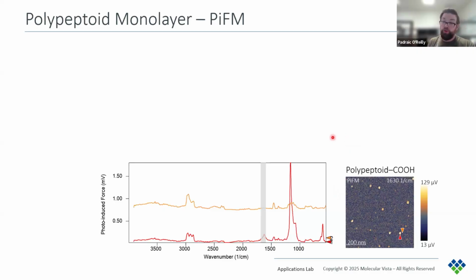So this is where we then return to PiFM. We remeasured one of the carboxylic acid samples, this time using a laser with an extended range. But we see that there are still these sub-monolayer fragments, as we would expect. You can see the red spectrum is taken on one of these bright regions. Again, it has this carboxylic acid group, but the orange spectrum shows nothing. And from the map, we see the majority of the area does not have any of these peptoid molecules.